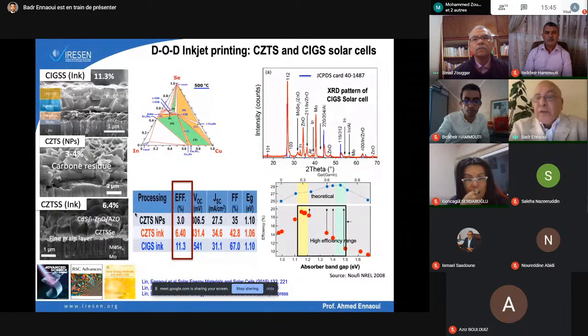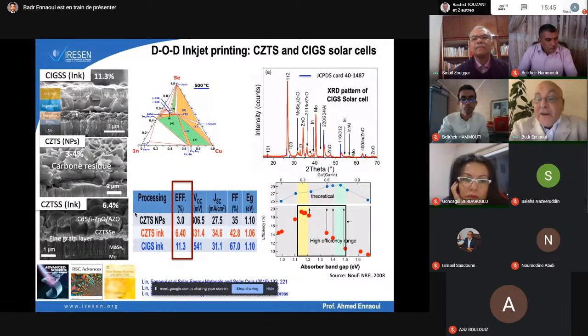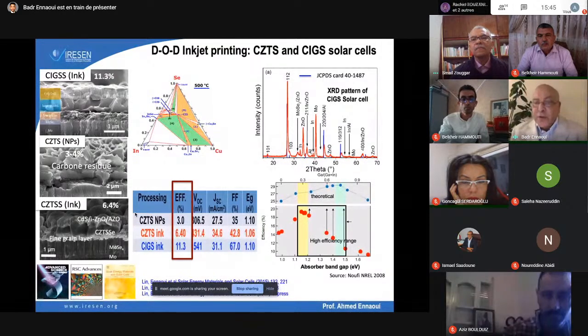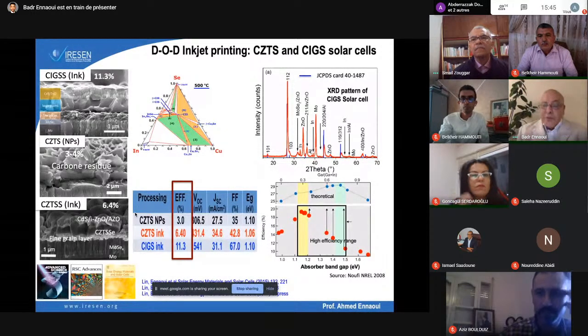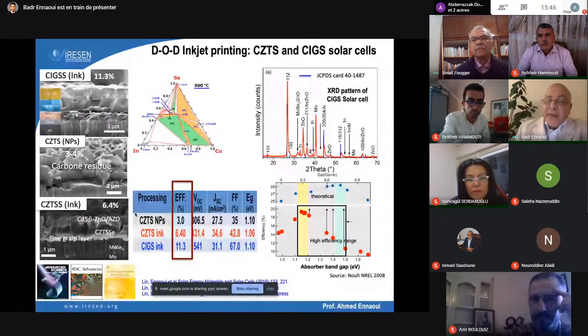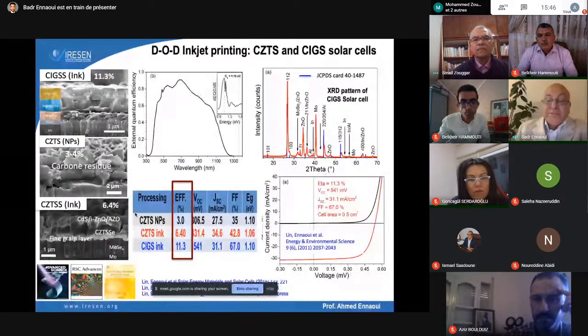As I told you, we use X-ray diffraction, Raman, and we find out the same problem that the scientific community finds: if you change, for example, if you substitute gallium with indium, as I show you here in a picture from the National Renewable Energy Laboratory, we still have this problem to increase the band gap and the photovoltage. That's our results, what we find here. The quantum efficiency I show you here.